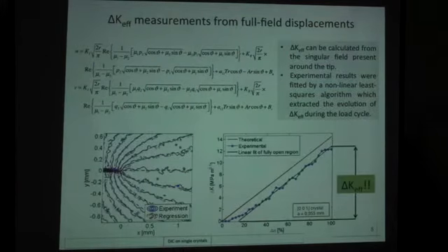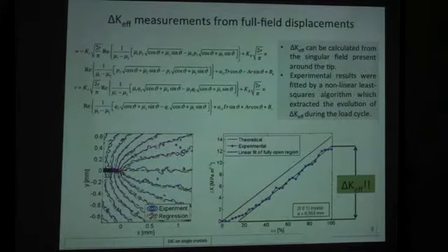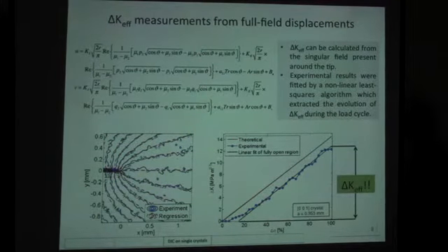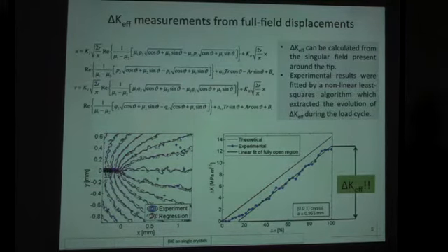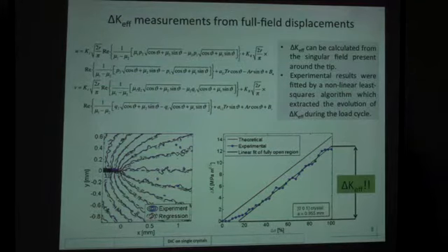So this is the fitting for one step of the load. This is the kind of response we can obtain. We start from the minimum load, we take several measurements of the stress intensity factor, and this is the kind of response. What we estimate is the final K, but it's not the absolute maximum K, it's simply an estimation of the delta K effective, because our reference image is taken at the minimum load. But you see there are some effects that are not exactly simply elastic.